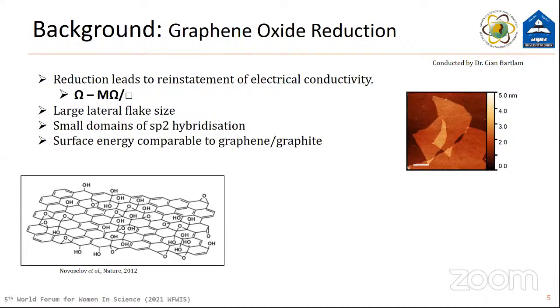The formation of reduced graphene oxide leads to a basal plane surface energy approaching that of graphene, and therefore suffers from the same problem of dispersion. The main advantage of using RGO over graphene is the greater versatility with regard to the dispersion approaches, particularly with regard to the scalability. Less energetic liquid phase exfoliation of graphene oxide allows larger flake size, which can give improved mechanical properties compared to that of small flake graphene, while still possessing high conductivity.